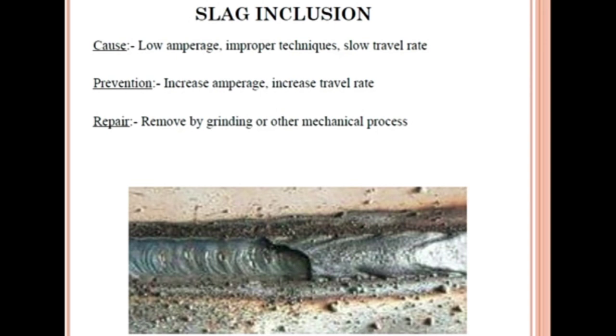The next defect that I can show you is slag inclusion. The example you can see in the picture. This is because of a low amperage setting, improper techniques, and slow travel rate. To prevent it, just increase the amperage and increase the travel rate. How to repair it? Just remove it by grinding or other mechanical process, such as using a steel brush.